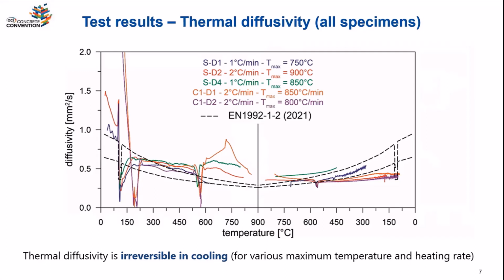And in heating, you have provisions in standards, notably in the Eurocode here, there are two curves that bound the behavior. And so we see that the trend followed basically these laws. It's not exactly, with some variability, but overall, what is in the standard captures the variation of thermal properties during heating. However, what was new was this right side of the plot, and what we found was that the thermal diffusivity was irreversible. Okay, so we didn't have the same type of variation during cooling that we had in heating.